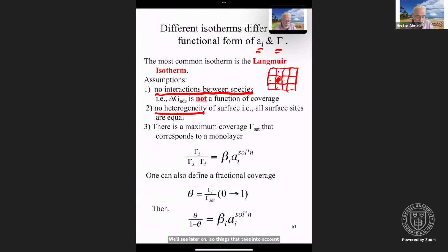The other one is no heterogeneity of the surface. That is, all surface sites are equal. And again, that can't be right. If you have a 1-1-1 surface, that's hexagonal, right? Versus a 1-0-0 or a 1-1-0, those are very different geometries, right? So here you have 1, 2, 3, 4, 5, 6. If this is a central one, this, in close contact, is a bit more expanded. And so even though we assume that all surface sites are equal, in reality, especially on well-defined single crystal surfaces, they're not.